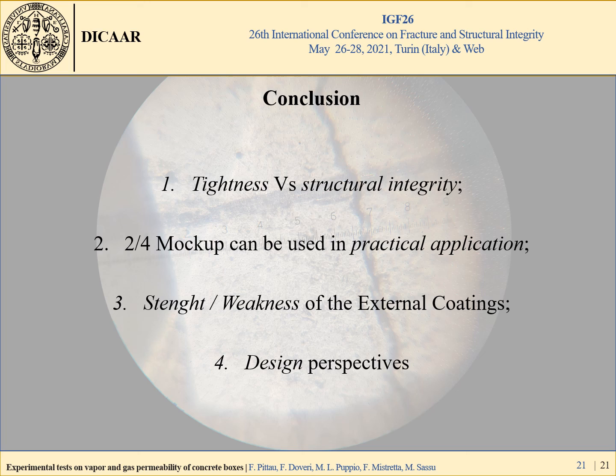Considering the limited thickness of the wall of the box and the poor quality of the concrete, the coating with mock-up A and C shows relatively good performance. We remember that none of the specimens in this campaign allowed an internal pressure, but this result can be attributed to very severe test conditions. The joints are a critical point to survey with care and attention. In the application of the coating, the preparedness of the worker and the initial state of the concrete surface play a crucial role. In order to ensure good performance over time, periodical checks of the coating have to be done.